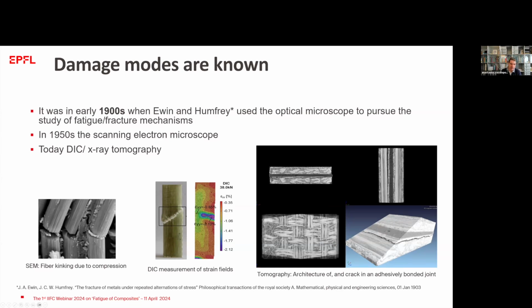And we can go much deeper. For example, with scanning electron microscope, what we see in this left figure is failure of fibers. When we go macroscopically with DIC, we can investigate and exactly locate the failure before it happens by checking online, I mean, in situ, during the test, measuring the strain at different locations of the specimen. Or we can work with tomography to investigate materials and their damage modes in situ in some cases, but also ex situ after failure, to accurately investigate the damage location and the damage mode.